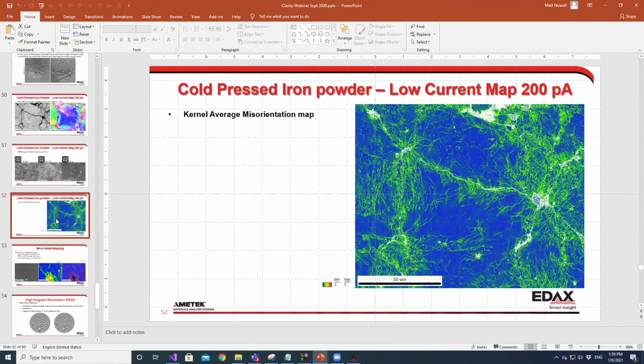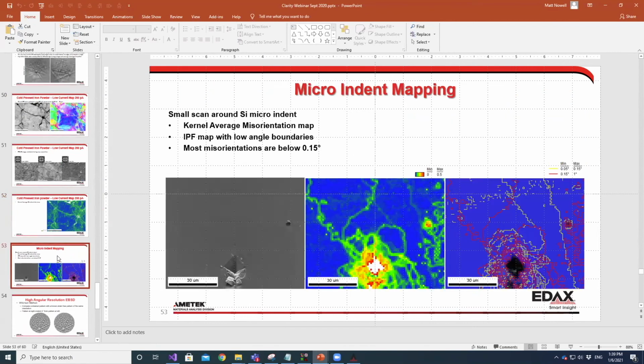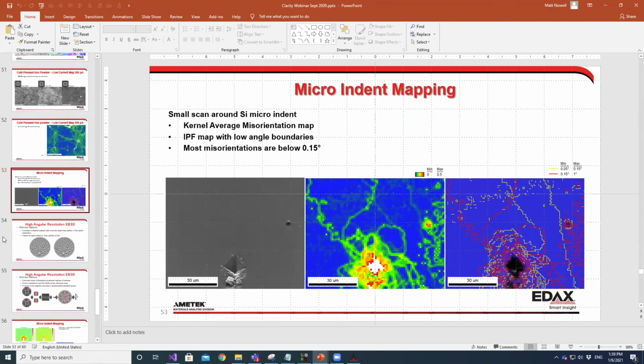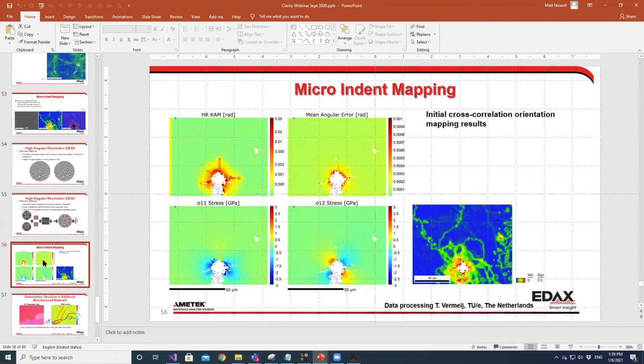And we've done other things. This is looking at just standard CAM maps with some of the high quality patterns. This is showing around an indent where we're looking at standard CAM maps. And we can take this data and do cross correlation results to start to resolve higher angular resolution CAM maps, or different stress maps in different parts of the stress matrix there.